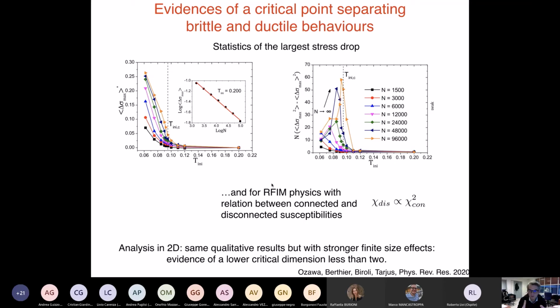All right, so this is what we find in simulation, which seems to go well with first the mean field result of the elastoplastic model, and also with the result on the random field Ising model. This was done in 3 dimensions, and then recently we repeated this in 2 dimensions, and we find very similar results, except that the finite size effects are stronger. But it looks like the transition is still there in 2 dimensions, which would mean that the lower critical dimension is less than 2. Well, if you can trust the simulation, this is probably due to the fact that the interactions are long range compared to the ones in the random field Ising model, which are short range.